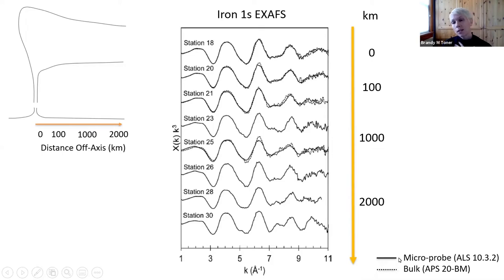And what you see in the solid lines is microprobe data from the Advanced Light Source 10.3.2. And then over plotted, where it was also collected, in dashed is data from the bulk beamline at the Advanced Photon Source 20 bending magnet. And so you're spectroscopists, you're already looking for patterns as you move off axis, good for you. You'll notice they're pretty similar, surprisingly similar. This was not expected by me or anybody else that I talked to, but there are some differences.